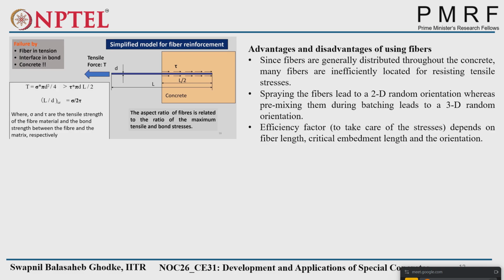So what are the advantages and disadvantages of fibers? Since fibers are generally distributed throughout the concrete, many fibers are inefficiently located for resisting tensile stresses. That's why I said distribution is very important. Spraying the fibers leads to 2D random orientation, whereas pre-mixing them during batching leads to 3D random orientation. Spraying means, after the concrete is prepared, we just spray the fibers over that concrete and then mix with some spatula or something like that. And pre-mixing means we mix them with the dry mixing itself. That is called 3D random orientation.